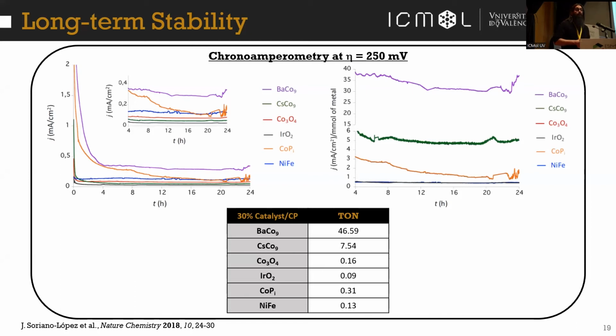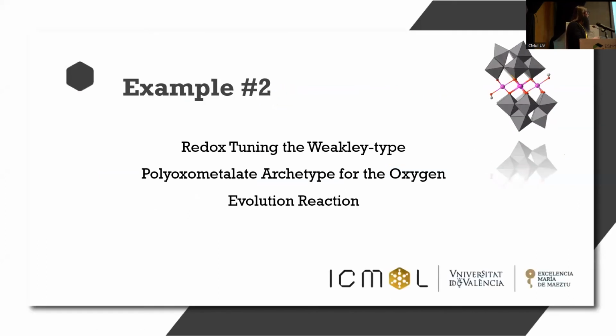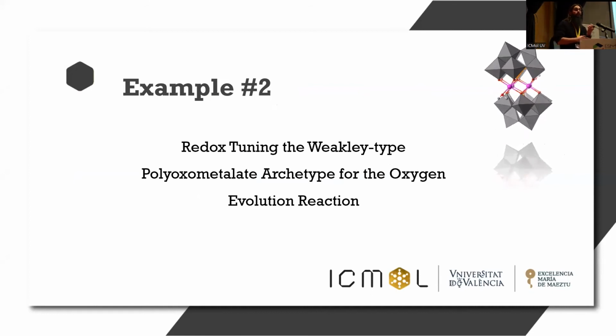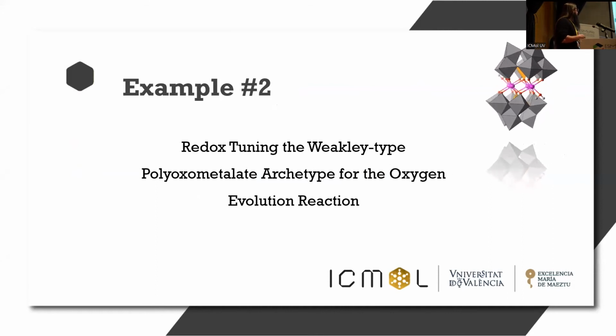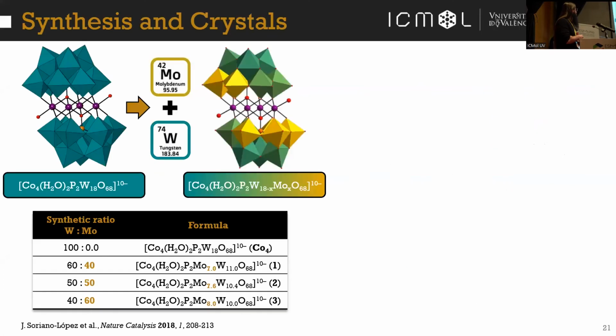than any other catalyst. So now I'm gonna show you the second example here, and this is regarding the fine-tuning of polyoxometalates to increase the activity. So in this case, we took this cobalt-4 structure, and the idea was to introduce some molybdenum atoms to replace some tungsten in the addenda atoms. This is known as addenda atoms.